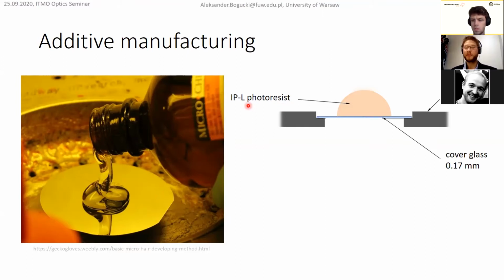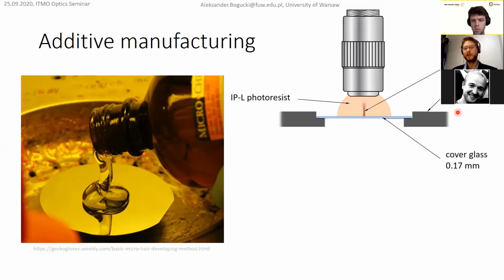So we use IPL photoresist, but there are plenty of available photoresists on the market with different properties. This photoresist is on top of a cover glass, a microscope cover glass, and is mounted on a piezoelectric stage. And by using a femtosecond laser, 780 nanometers, in the focus of the laser, polymerization occurs. So this photoresist becomes a solid polymer.